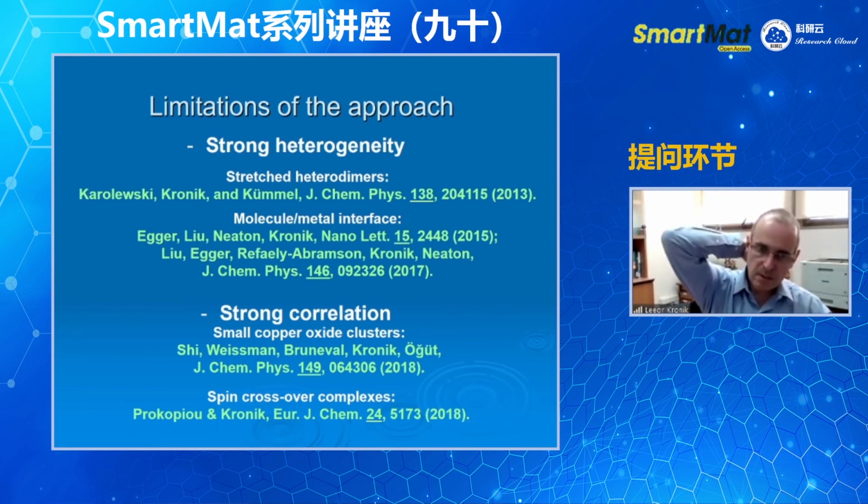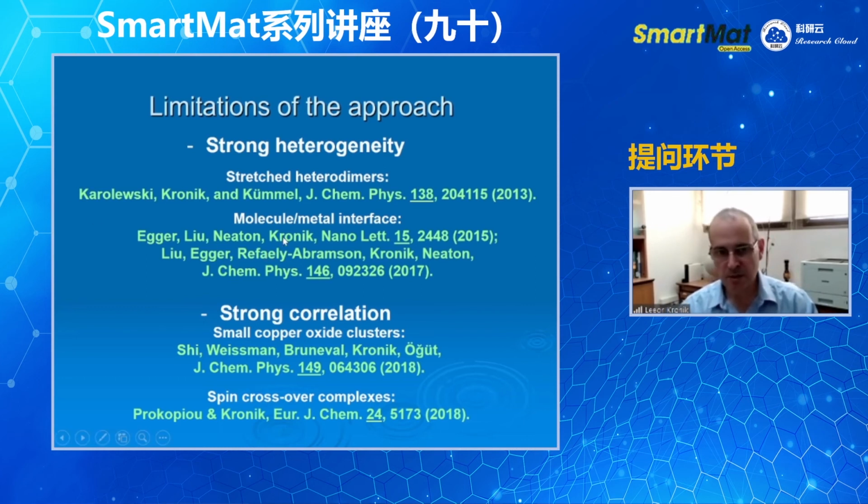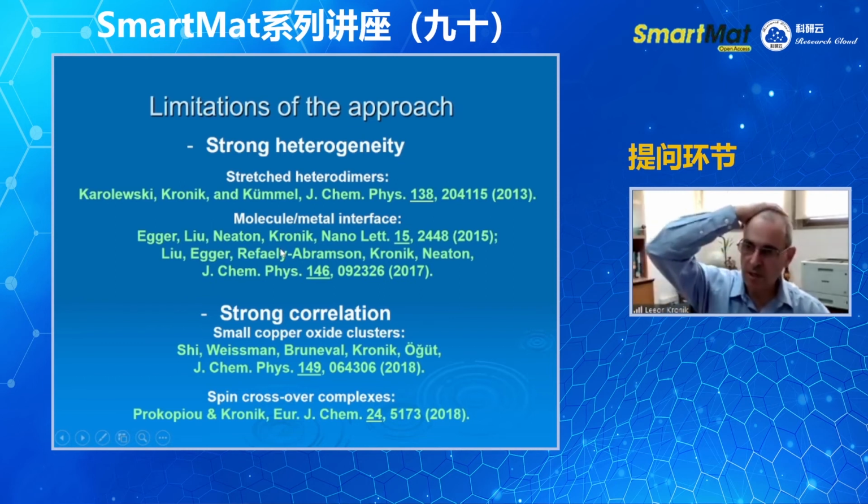Basically what Zhenfei and David showed is that when you have a molecule that's weakly adsorbed on a metal, you can get around this problem by calculating the image charge from the metal. And then if the molecule is more strongly bound, you can find an effective dielectric constant that mimics the response from only the metal. That's the content of these two papers.